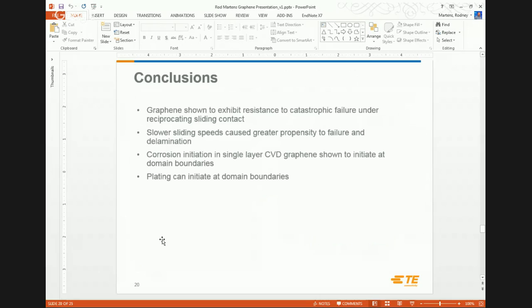So just a few quick conclusions here. At a high level, we were able to show that it is somewhat gas impermeable. We could limit oxidation and generate low contact resistance with the graphene. We found some indications of slower sliding speeds causing higher failures. And then also we've shown where the corrosion and plating can initiate in the grain boundaries.